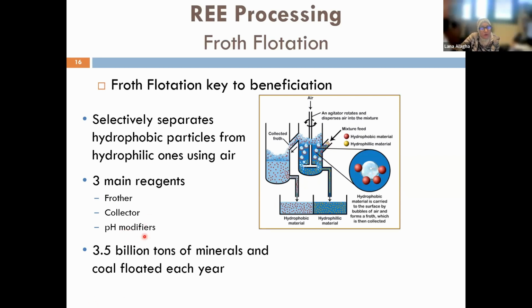But again, before you mix your ore with water, you have to modify the pH, because the collector is added to render the surface of the mineral hydrophobic. In order for the mineral to be attached to air bubbles, it has to be hydrophobic, because the interaction between the mineral surface and air bubbles is through hydrophobic interactions.